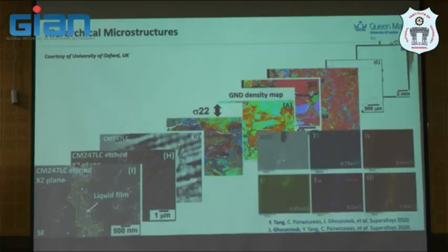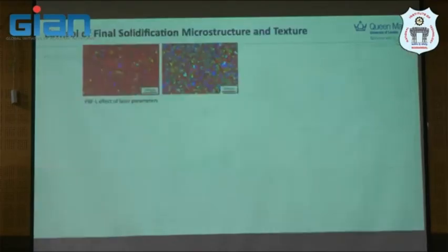And this liquid film, if we look further into the sample, you will see some more hafnium, and then some carbide and tantalum in this crack region. So it's quite amazing work that we use all the characterization techniques to provide insight into the defect formation during the process. And finally, we want to control the structure. There is no doubt about it.